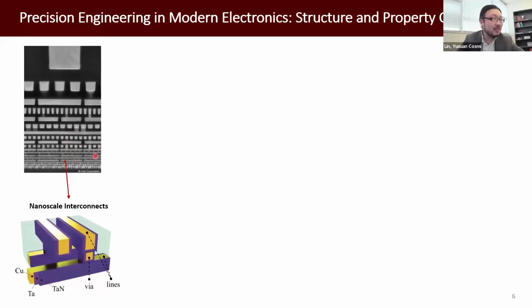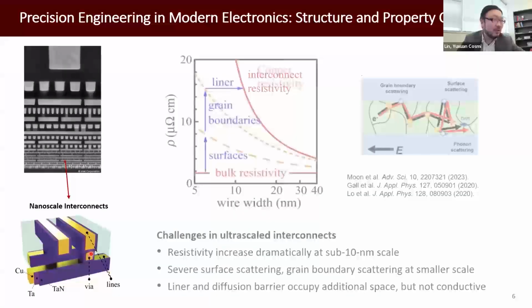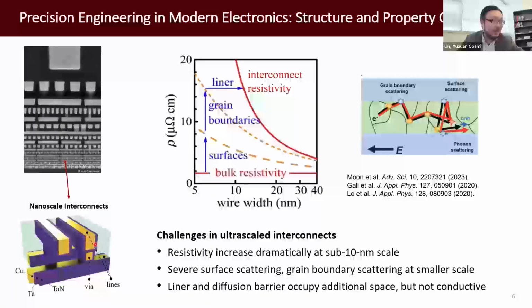And there are like tens or even 100 different metal layers. But for the very bottom layer, because the transistor dimension has been scaled down to super small, maybe 10 nanometer footprint, the interconnect has to be on a similar scale or even smaller. But when people are trying to scale down the copper-based interconnect to below 10 nanometer scale, the resistivity increased very significantly. This is a resistivity, not a resistance. But even for resistivity, there's a huge degradation.